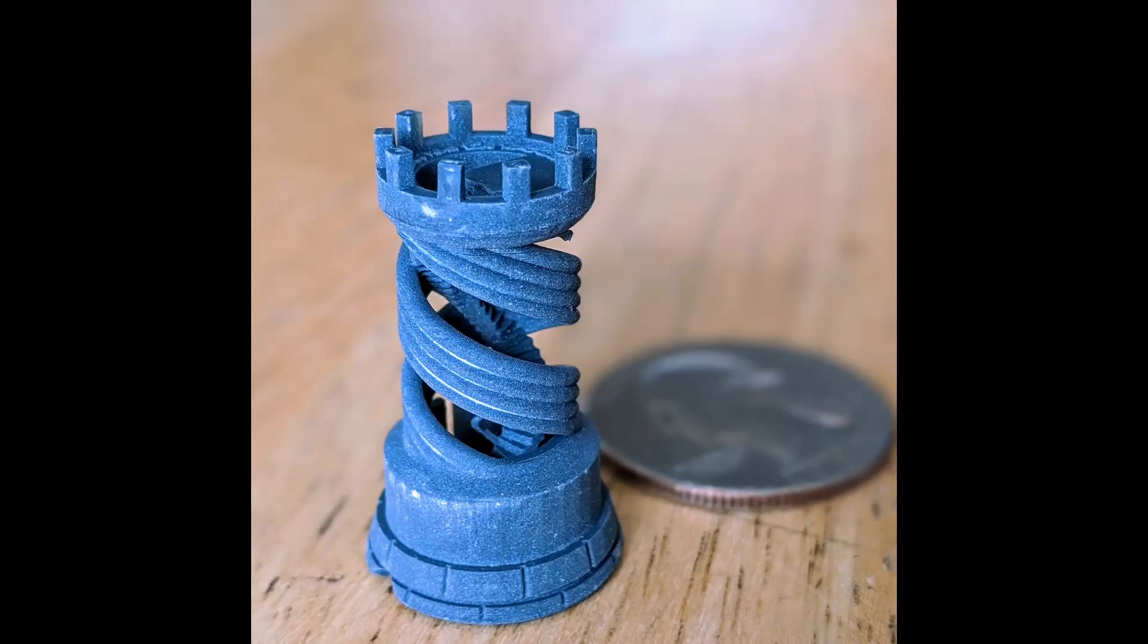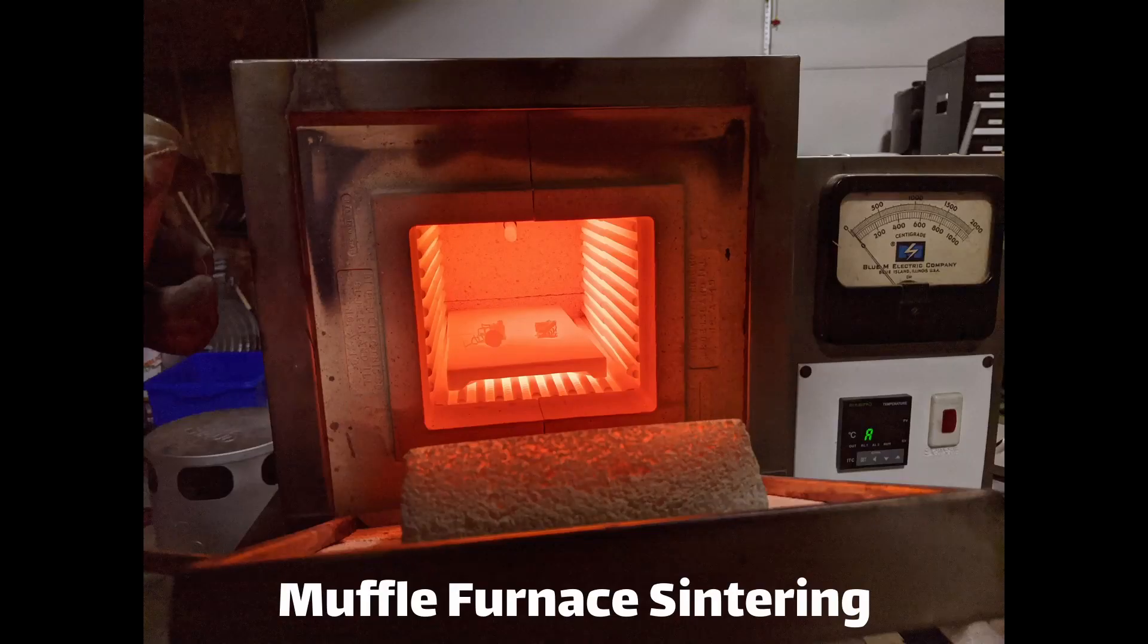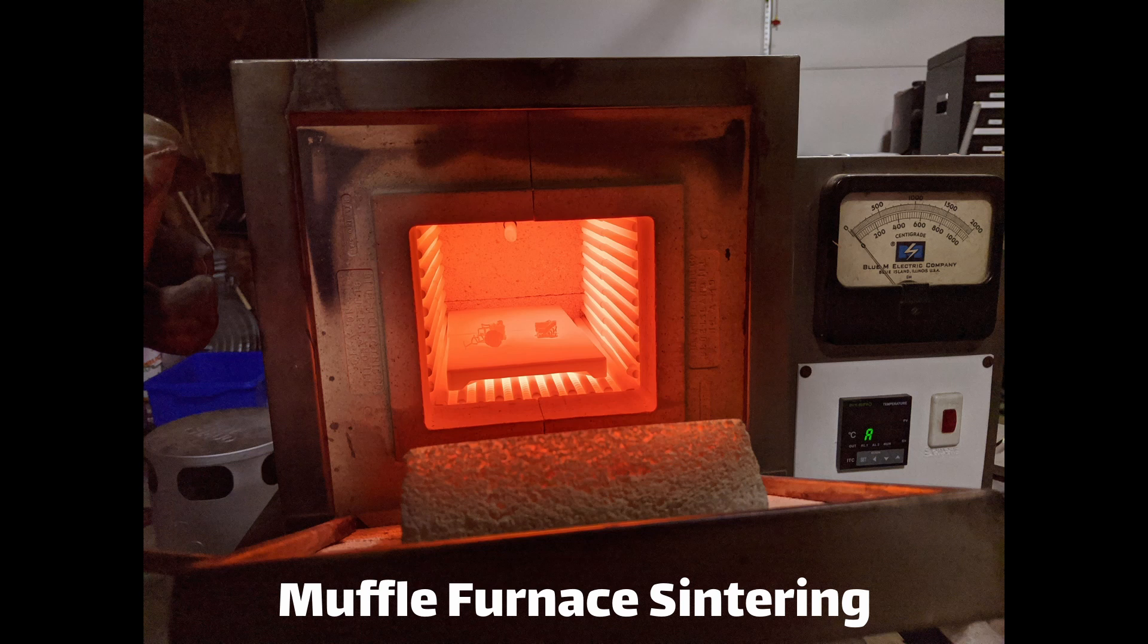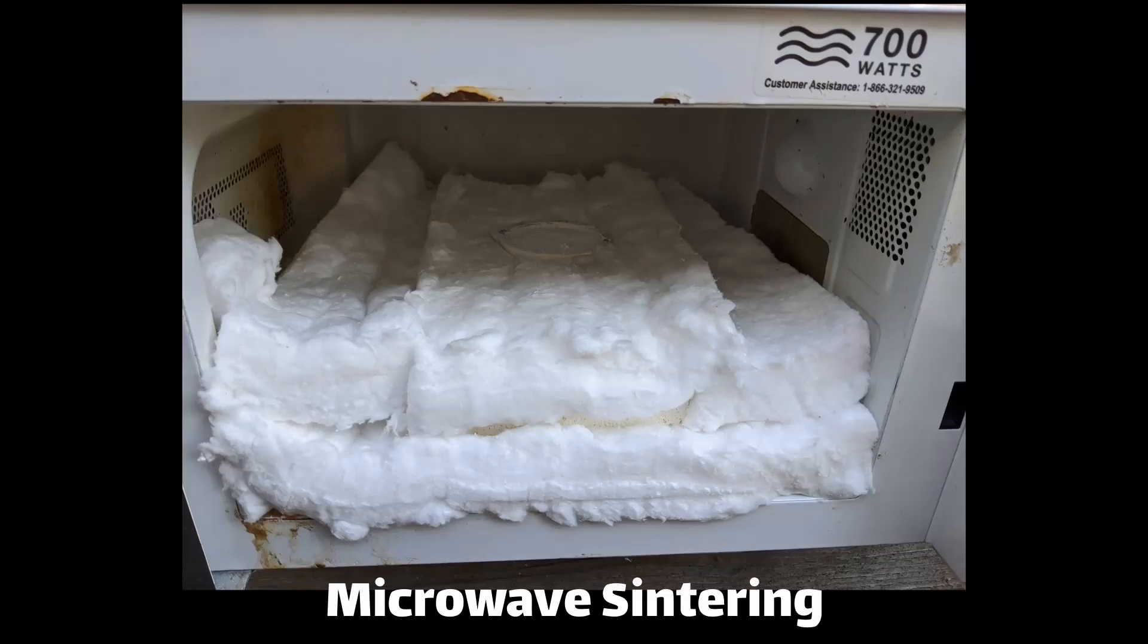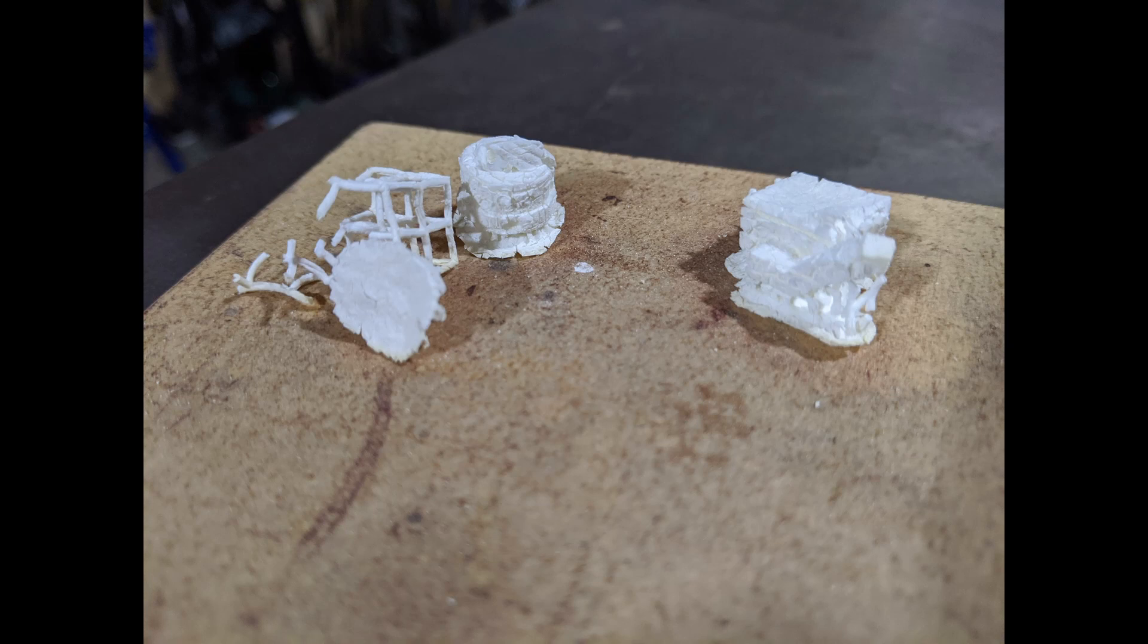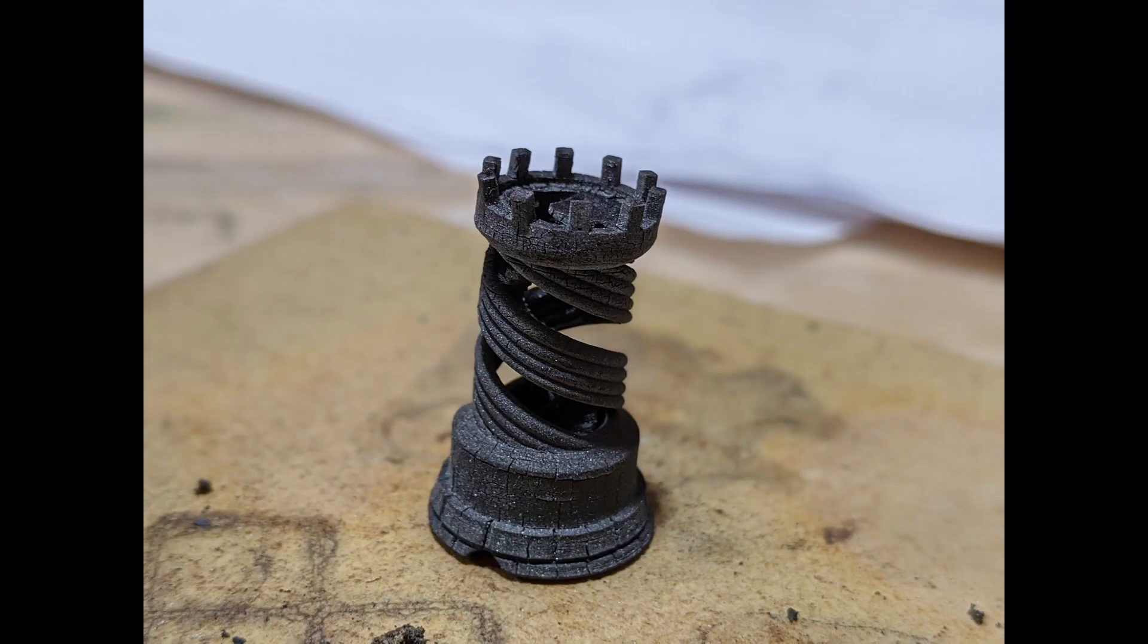I've always been interested in additive manufacturing for ceramics, and over a long time I was playing around with adding different ceramics, mostly aluminum oxide, to off-the-shelf SLA resin. If you can get a high enough loading of aluminum oxide into this resin, you can print with it and then sinter and bind it together to make a ceramic part. There's some chemistry involved because you need to keep the aluminum oxide in suspension. You can see in this image the plain resin on the right just doesn't keep alumina, but if you play around with charge potentials and pH like on the left, you can actually keep the aluminum oxide pretty well suspended. If I remember correctly I was using citric acid on the left. This is a really deep rabbit hole - you need high enough loading of the ceramic, and then you also need all your burnout and sintering schedule to be perfect or else you just get an oxidized mess like you see here.